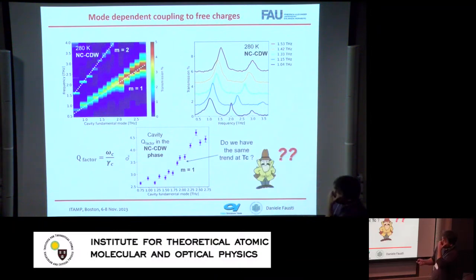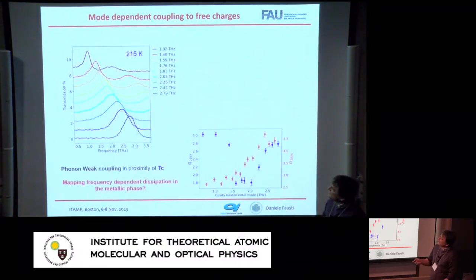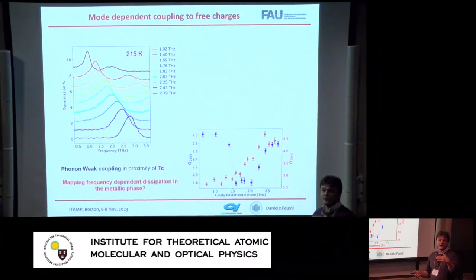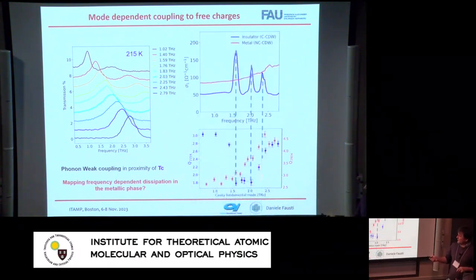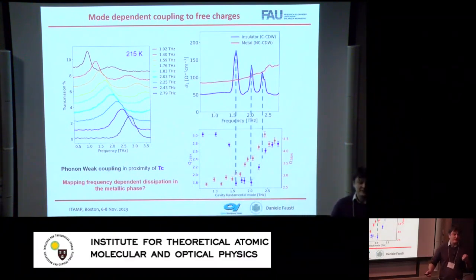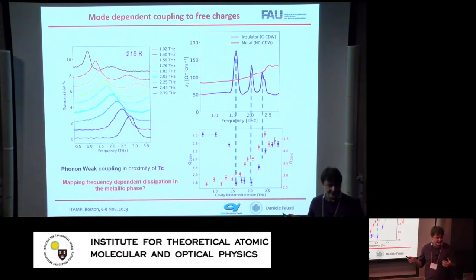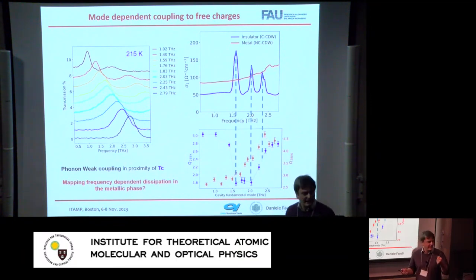But what's interesting is what happens just above TC, in the situation where I have mostly the Drude response, so I don't see the phonon in linear response. I see that the quality factor of my cavity is a non-monotonic function. And if I look at which frequency I have this non-monotonic behavior, I find the frequency of the phonon mode of the symmetry broken phase. So in some sense the phonons are no longer visible in linear response, but they still participate in the dissipation. The cavity is mostly coupled to free electrons, but there is a scattering possibility to the phonon mode.